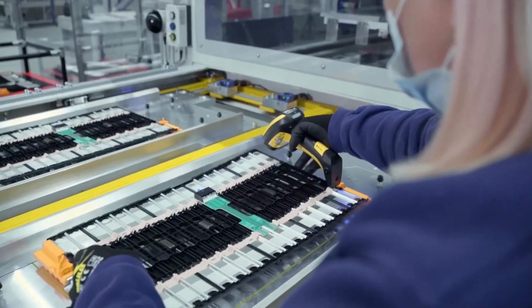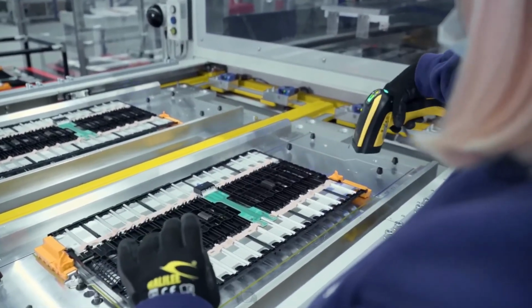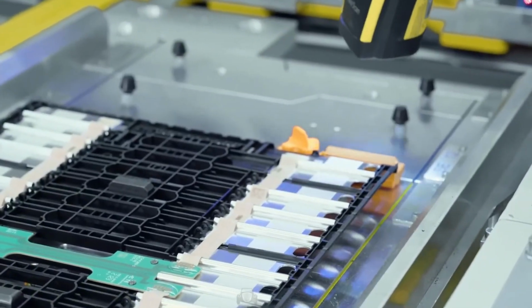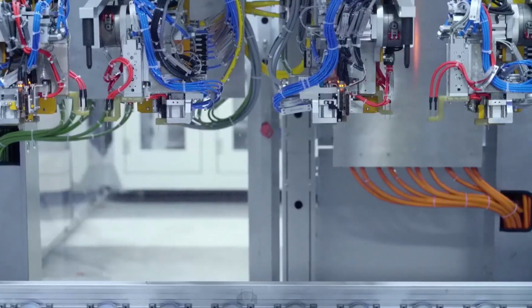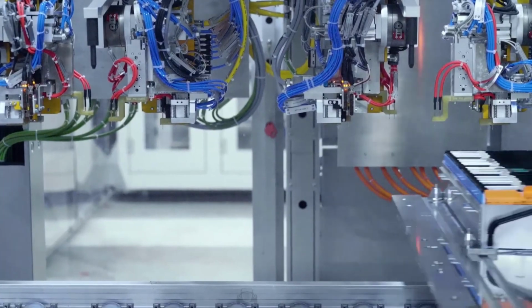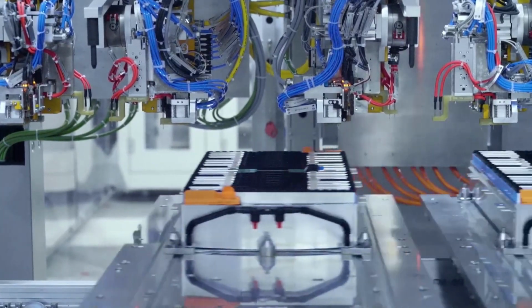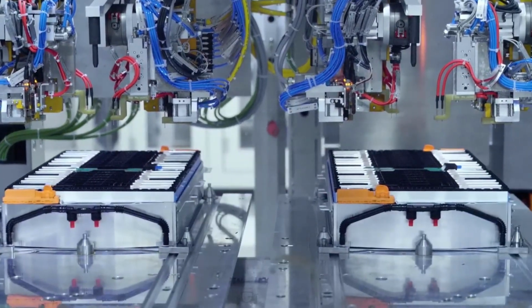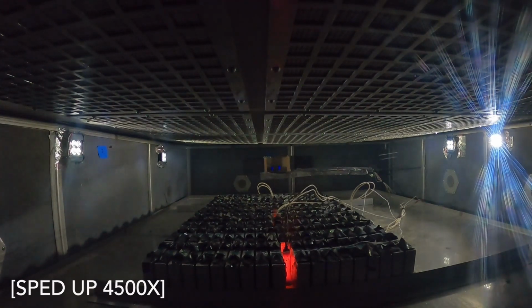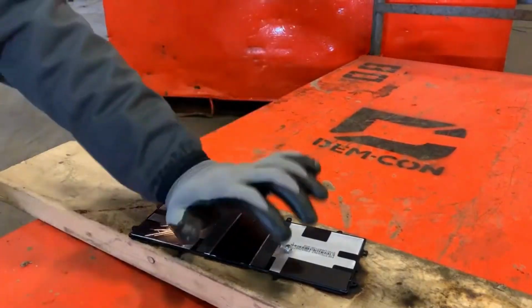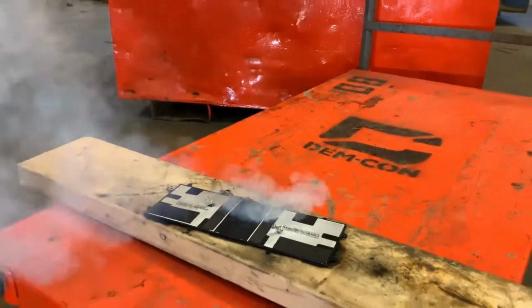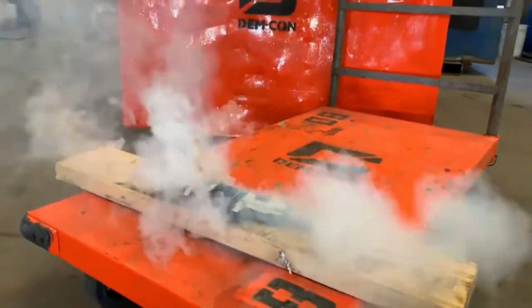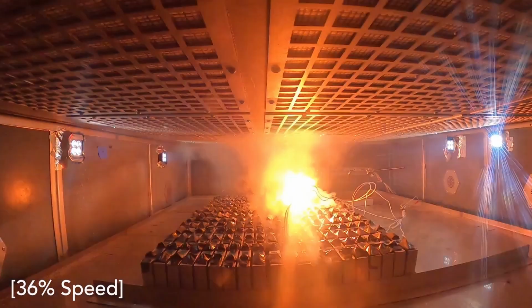The battery is charged for the first time, waking up its chemical reactions. This step is slow and delicate. Batteries sit on shelves for days or weeks, like fine wine aging in a cellar. Engineers monitor them for voltage drops or swelling. A puffy battery is a bad battery. Then they are baked at 140 degrees Fahrenheit, frozen at negative 40 degrees Fahrenheit, punctured with nails, and crushed under weights. If they catch fire or leak, they're tossed.